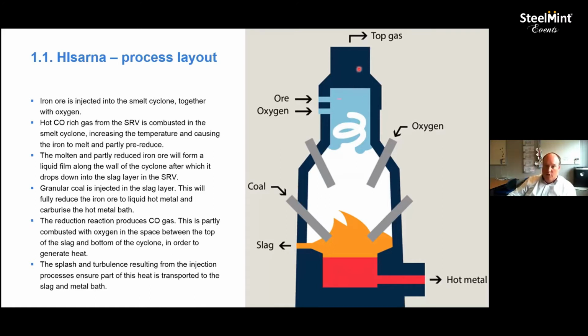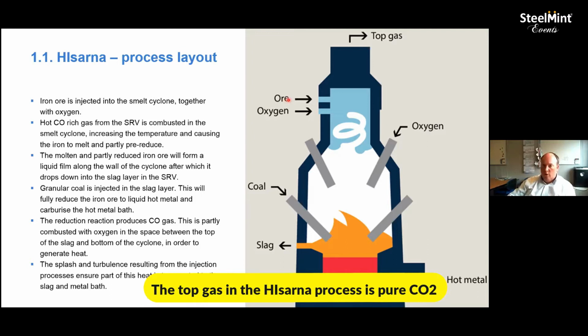Gas temperature in the cyclone anywhere between 1600 and 2000 degrees, and the top gas that escapes is pretty much pure CO2, and the only reason why at the moment it's not completely, is because we inject the iron ore with compressed air, which has of course nitrogen in it, and we inject the coal with nitrogen for safety reasons. But we've already demonstrated that we can also inject the coal with carbon dioxide, so CO2, and there is no reason why we couldn't do the same with the iron ore. And if you do that, you have top gas that is pretty much pure CO2.